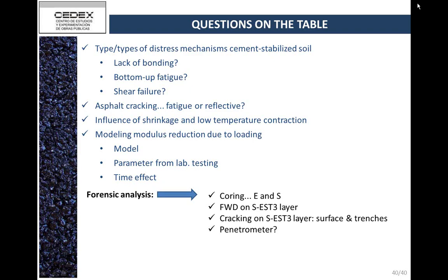My comments really are, if you have the same interface and you have one that's tacked with a relatively stiff material and one that's tacked with a relatively soft material, then the condition of the bond will drift more to full bond and more to no bond as you go from stiff material to soft material, and that's an effect that I think can be independent of this full debonding that leads to a complete change in the stress distribution. You know what I mean? I understand. The only thing I can comment is that we found that if you can change the surface texture so that the bond is also enhanced by a horizontal shear resistance, that also helps to do exactly what you're saying.